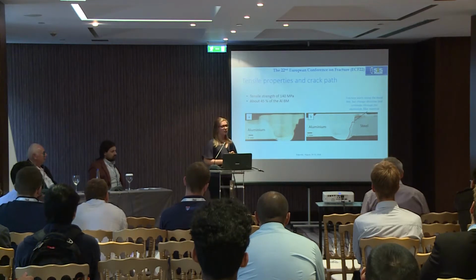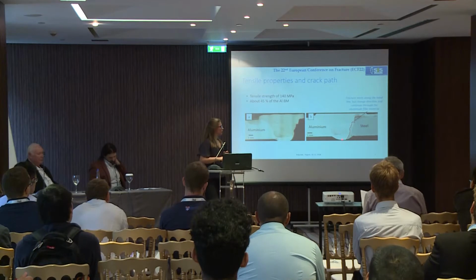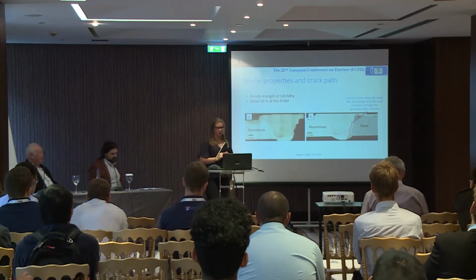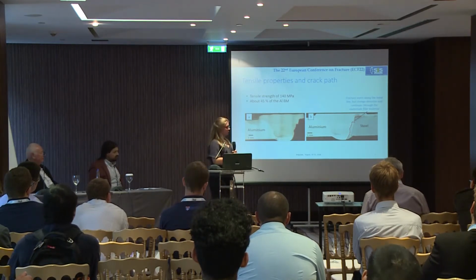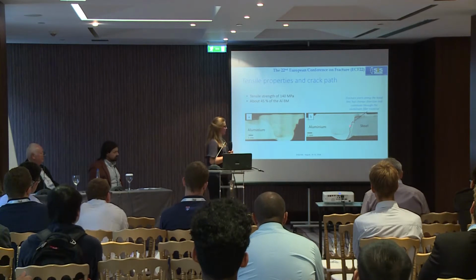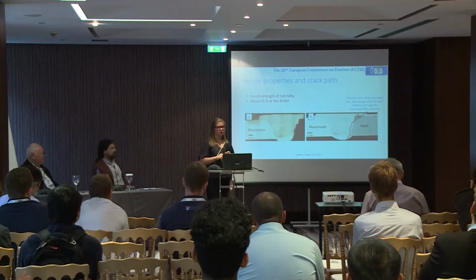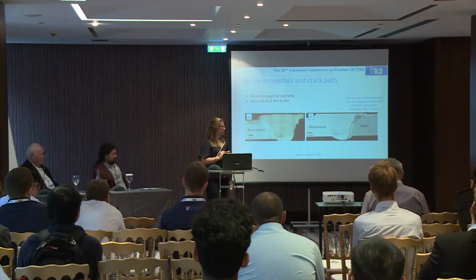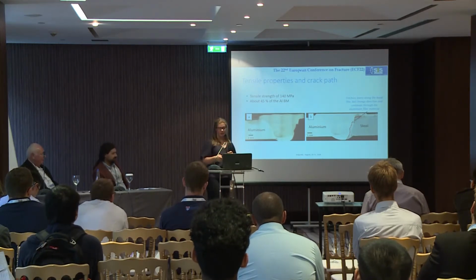And this means that sufficient bonding is obtained through most of these parts of the joints. Also, you can see that this is quite similar to where we found the lowest point, or lowest hardness, in the previous slide.